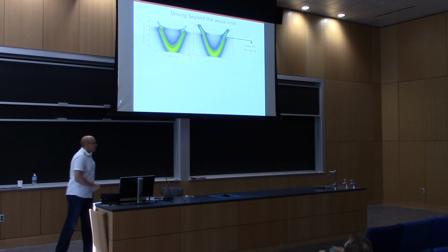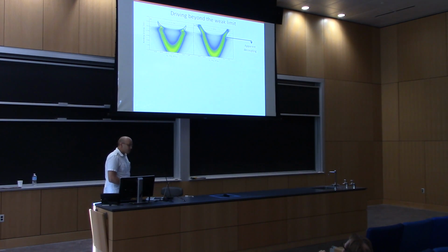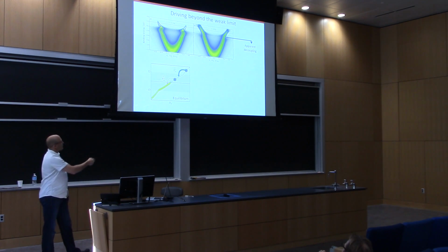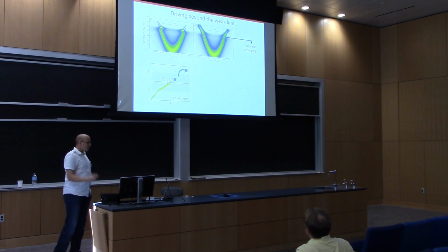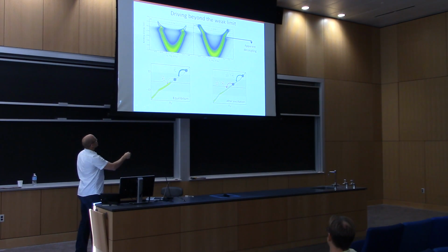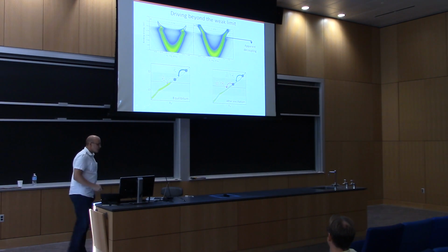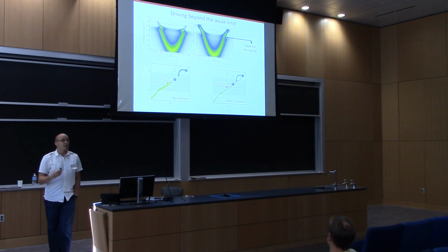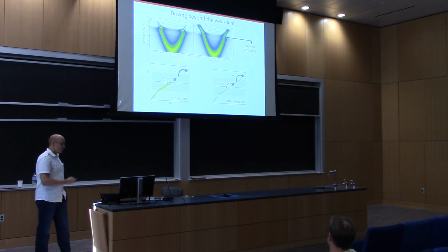This comes with an apparent decoupling that Jim talked about, and I'm going to talk about the origin of this a little bit. This is my equilibrium picture. Now in non-equilibrium, what I get is I've just redistributed some of these electrons, which means that this scattering process, which was previously forbidden, I can now do. This one, which was really easy, is now a little bit harder, and that causes this change in the scattering rates. Just a phase-space restriction at this point.